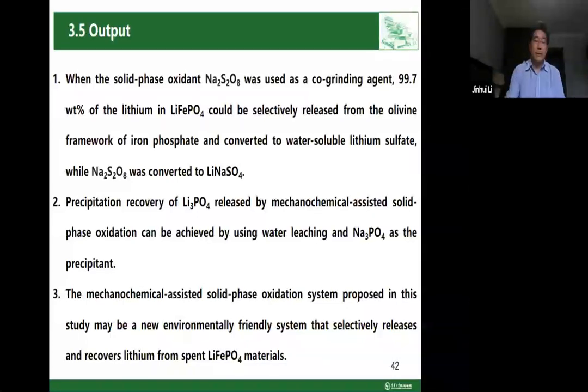So based on this, we can very briefly conclude that the first is, when the solid phase oxidant persulfate was used as a co-grinding agent, 99% above of the lithium in lithium iron phosphate could be selectively released from the olivine framework of iron phosphate and converted to water-soluble lithium sulfate, while sodium persulfate was converted to sodium sulfate.